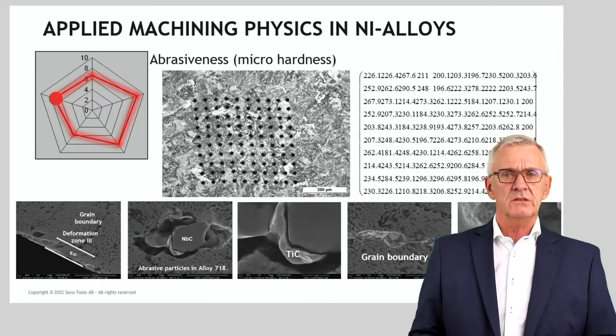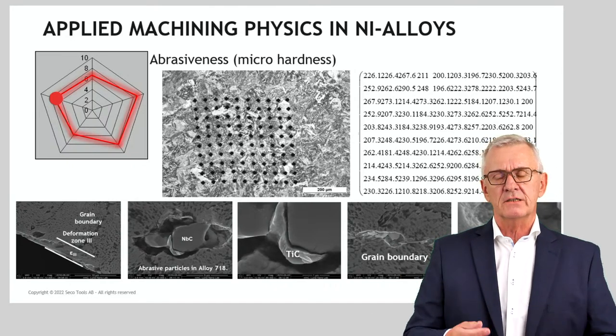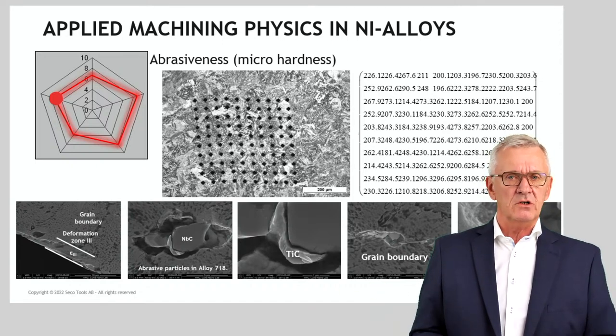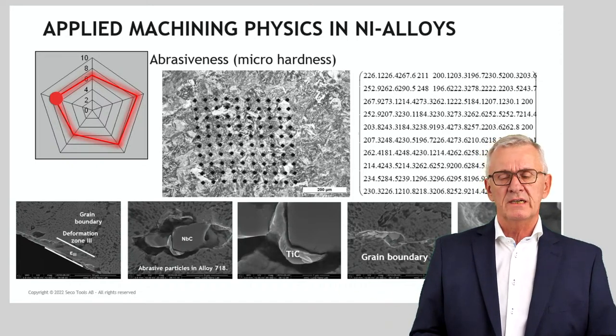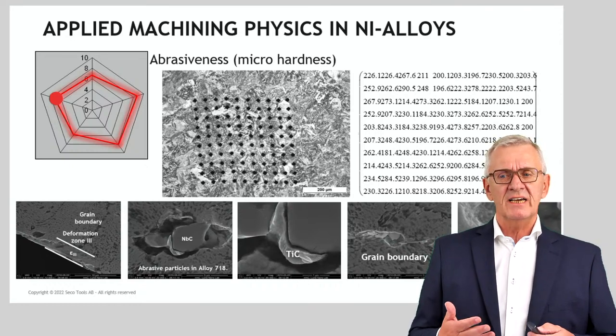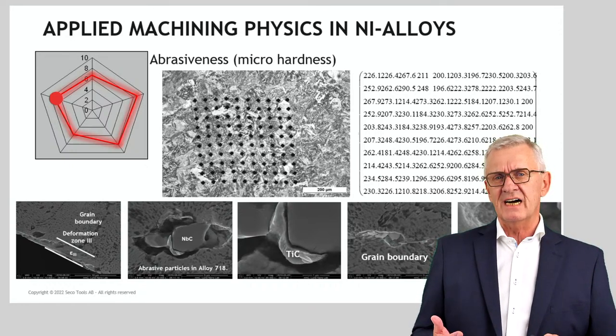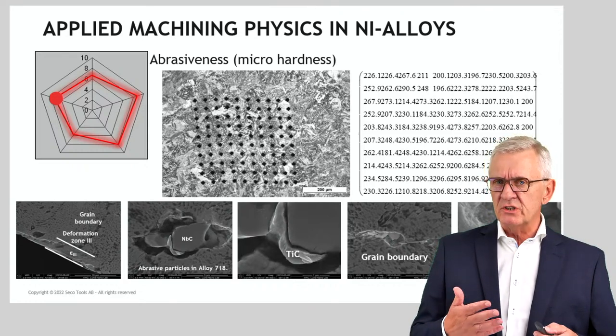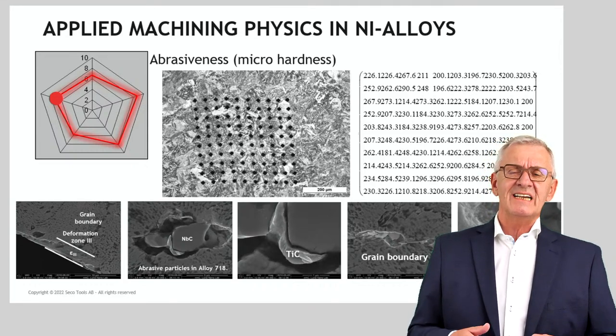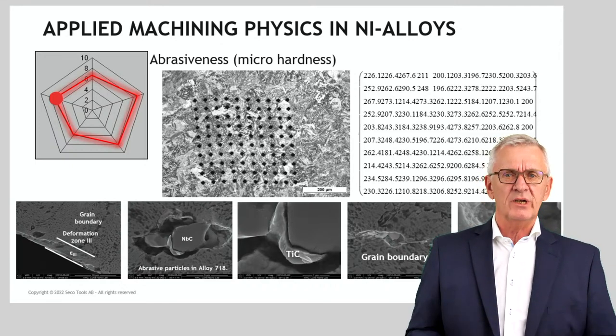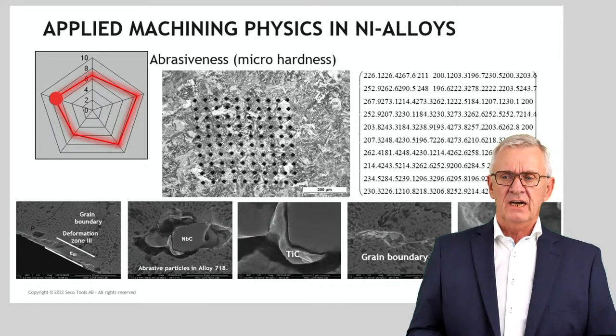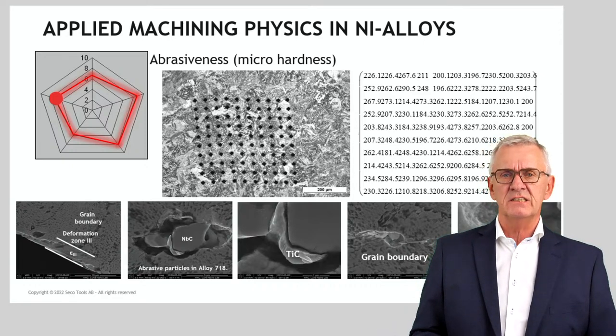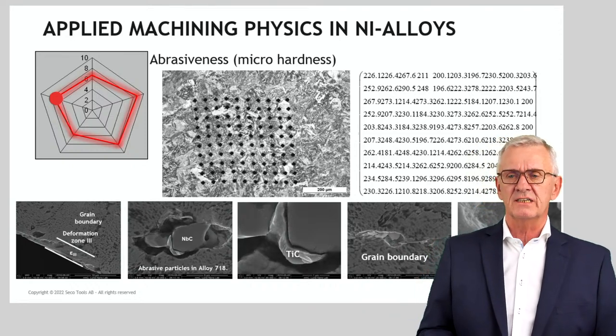How do we measure abrasiveness to come to a rational figure to express it? Well, we measure it through measuring micro-hardnesses. Now, not every company has a micro-hardness measuring machine, but that's the scientific way. There are more pragmatic approaches. I'll show you directly one. But micro hardnesses, abrasiveness, you know, in superalloys, there are, from a metallurgical perspective, quite some things that lead to materials showing certain abrasiveness that we did not expect. I think of precipitation hardening effects. I think of carbide formers in the structure and things like that.